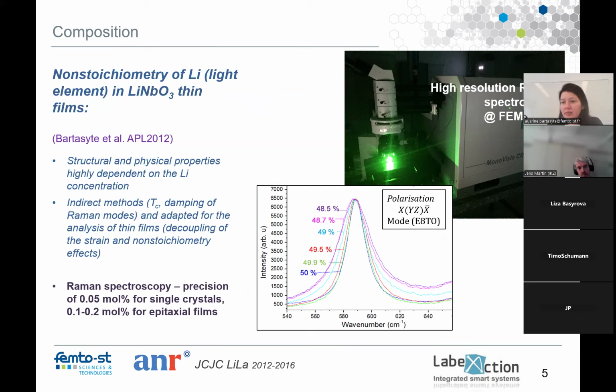And even when you buy a single crystal, the composition is never indicated in mole percent. In most cases, for example, if you buy lithium tantalate, they will say the Curie temperature is 603 degrees Celsius, or for a stoichiometric crystal, it will be 690 or 700. So basically, we use the physical properties to indicate the composition of a crystal. Even for single crystals, when we characterize the composition, we use indirect methods. It means that we measure the properties, and then we estimate how much lithium we have. So we do calibrations as a function of stoichiometry, and then we use these calibrations.